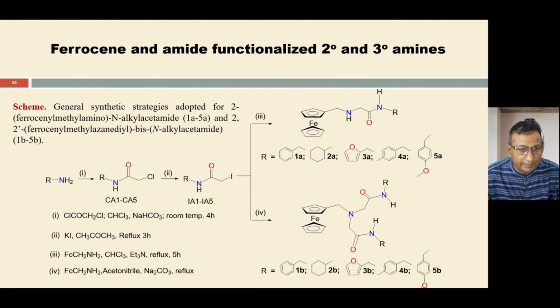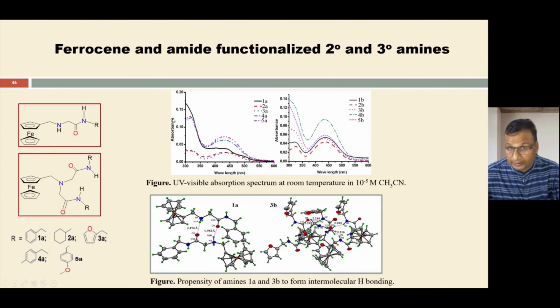So for that, keeping that in mind, we have developed the synthesis of various amine precursors, secondary amine precursors, suitable for the development of corresponding dithiocarbamates and their complexes, along with the tertiary amines. All the molecules have been characterized well with various spectroscopic as well as crystallographic studies. The appearance of a UV-visible band around 450 nanometer corresponds to the ferrocenyl group because of the charge transfer. And these molecules have shown the ability to form a number of intermolecular as well as intramolecular hydrogen bonding interactions, as revealed by their single crystal X-ray diffraction study.